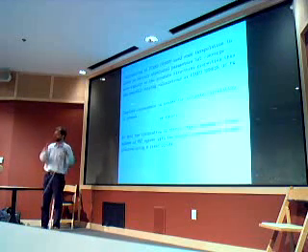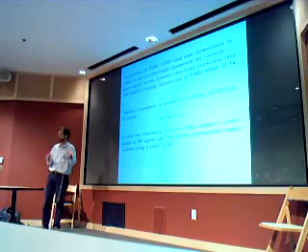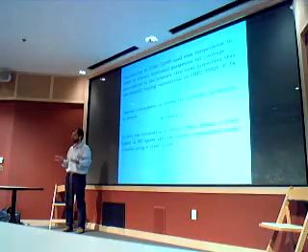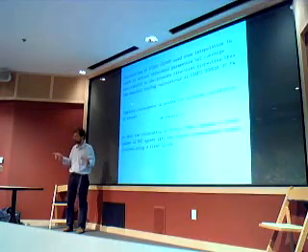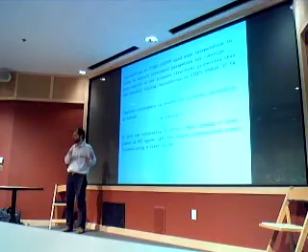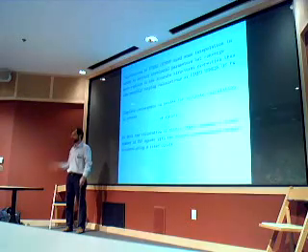So it really comes from the Fourier transform of the atomic wave functions. You take your pseudopotential in the radial grid in your atomic form, so you do not have any plane waves or anything. You take your wave function in the radial grid, you make the Bessel transform, and this gives you the Fourier transform, and then you see where this Fourier transform decays.